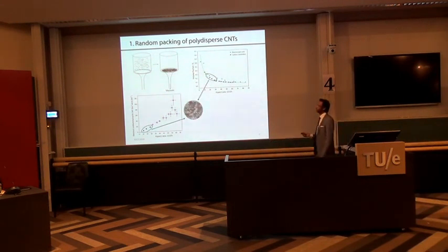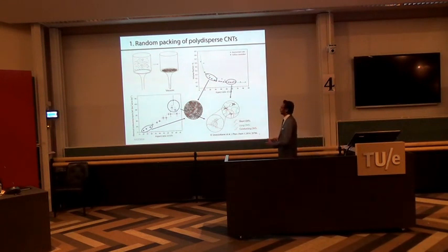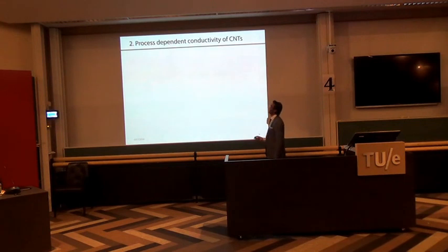In the case of low aspect ratio, because of the large number of contact points, the contact resistance plays a massive role, and the electrical conductivity decreases. However, increasing the amount of longer tubes forms the global packing, and the short tubes form the conduction knots. At a specific composition, the resistance of these conduction knots under the connecting long CNTs gets optimized and gives you the higher conductivity.